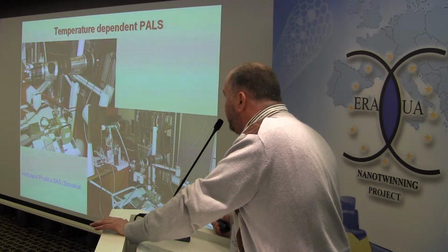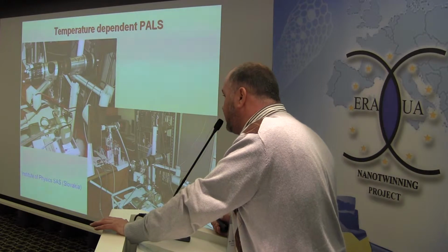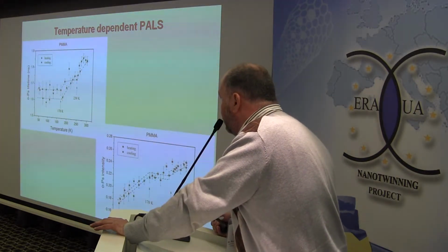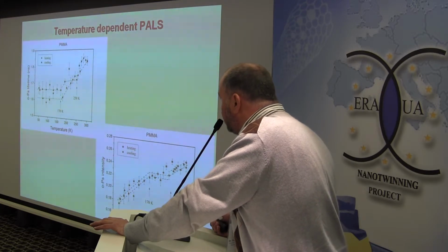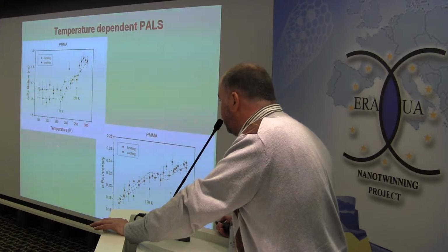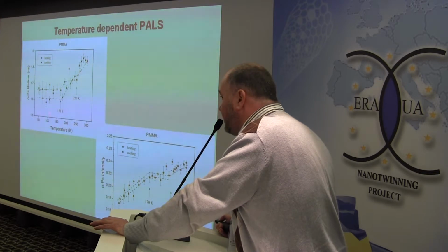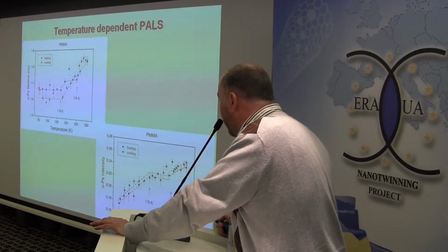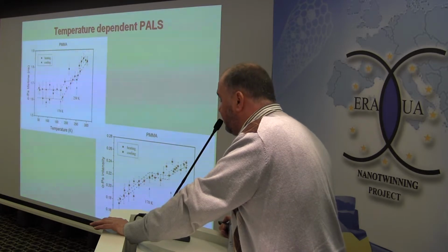We carried out this research work at the Institute of Physics in Slovakia. Here we see the orthopositronium lifetime as a function of temperature and the orthopositronium intensity as a function of temperature. We see threshold temperatures at 170 and 250 K for orthopositronium lifetime and intensity.